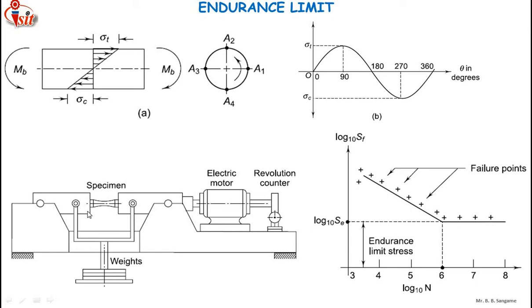So in this machine, the specimen of the material which is to be tested for fatigue strength or endurance limit is mounted, and the load is applied and the rotations are given. It is started with the minimum load and minimum rotations, minimum RPM. Observations are taken when the first crack appears for a particular applied load and a particular number of rotations. And you can see that as the load is increased, the number of cycles is reduced.